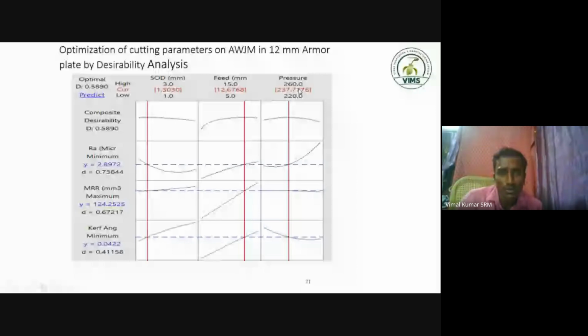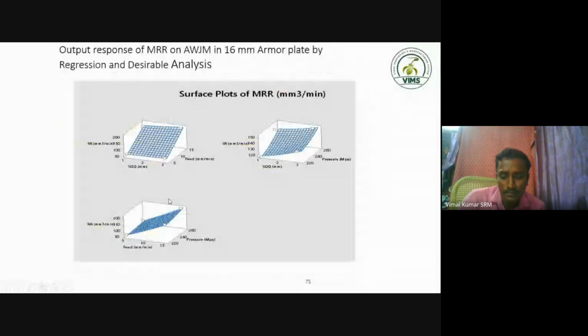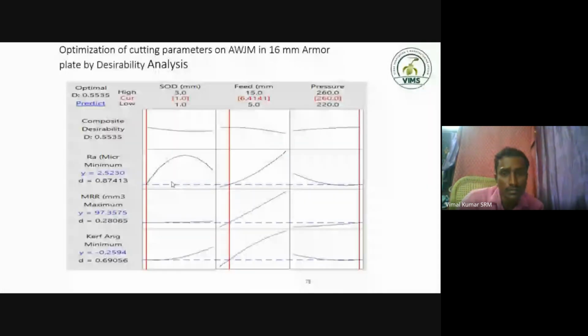These values are known. But we don't know the surface roughness, MRR, and kerf angle for a new thickness of the armor grade steel. We know about 12 mm, 16 mm, 20 mm, because we already worked on that material and got the results, but we don't know what the MRR and kerf angle are when changing the thickness. So in this condition, we go for optimization techniques, in the sense of regression analysis. We can slightly move the straight line, and it will show the values: the surface roughness value, the MRR, and the kerf angle. So we don't need to go for further trials.